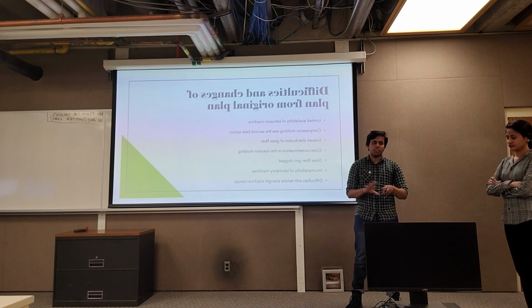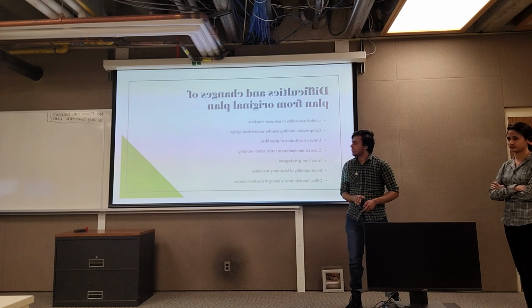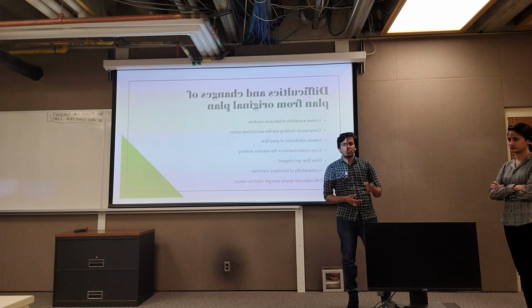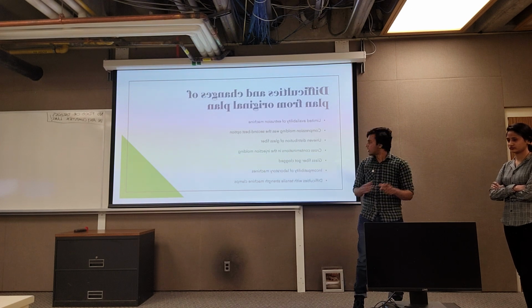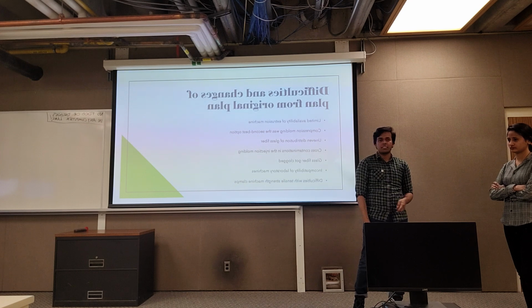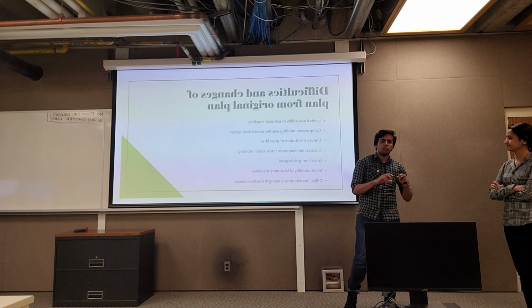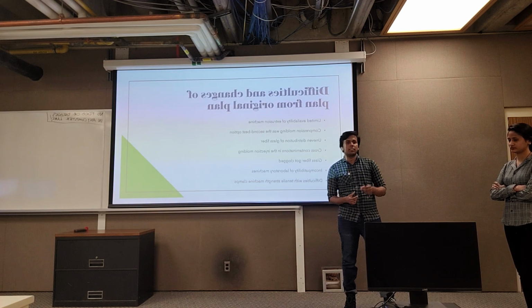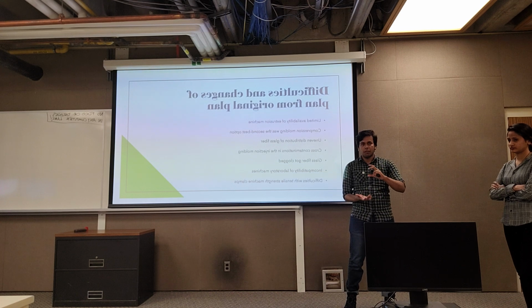Due to that, there was an uneven distribution of the glass fiber in the plates. And then in the injection molding, we noticed that there was always remaining material in the chamber. That remaining material caused cross-contamination in our dog bone samples. Also, when we were about to make dog bone samples of glass fiber reinforced materials, every single time the glass fiber got clogged in the chamber of the injection molding machine.